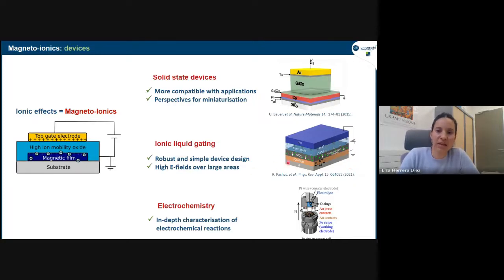So here, what you have is your magnetic film, and then you put this ionic liquid on top. The ionic liquid is basically a molten salt. It's a liquid, but it doesn't have a solvent. It just has positive and negative ions. So if you put it in a sandwich structure like this and apply a voltage across, you could get a huge polarization, because the ions would move towards the counter electrode, and you could get very large electric fields. And it's a very, very simple device geometry. You just put the liquid on top of your film, and it just works.